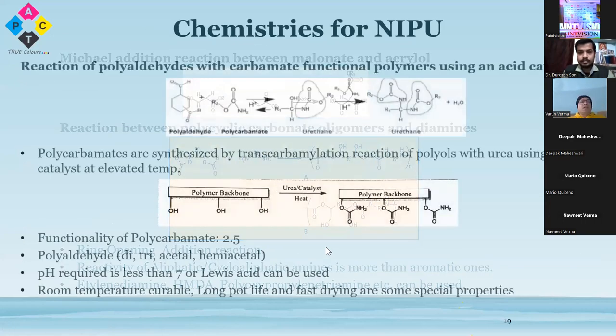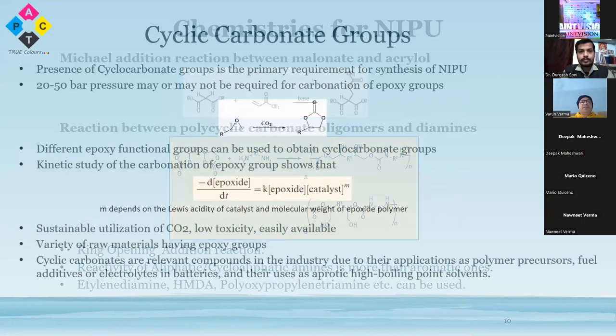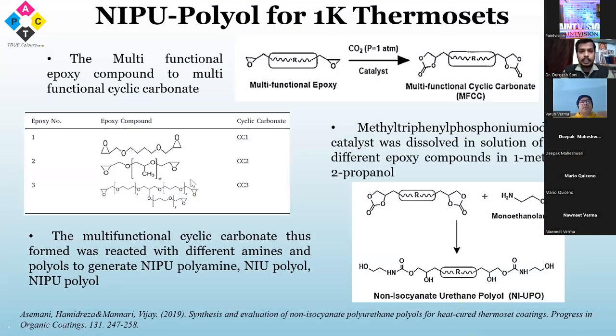So coming to the next slide. These are some works done by Professor Vijay Mannari, like this 1K thermoset coating synthesized by him. He used multifunctional epoxy groups, and using CO2 and a particular catalyst, he converted the epoxy groups into multifunctional cyclic carbonate groups, and after curing with monoethanol amine, he synthesized non-isocyanate polyurethane polyol. Once this polyol is synthesized, it can be cross-linked with conventional cross-linkers like melamine formaldehyde and urea formaldehyde resins in which methylol groups are present.